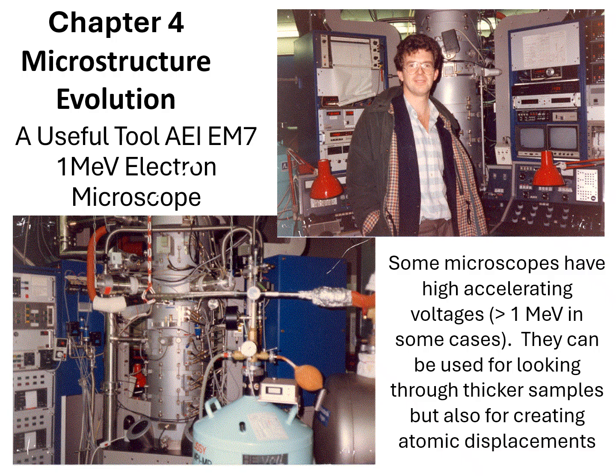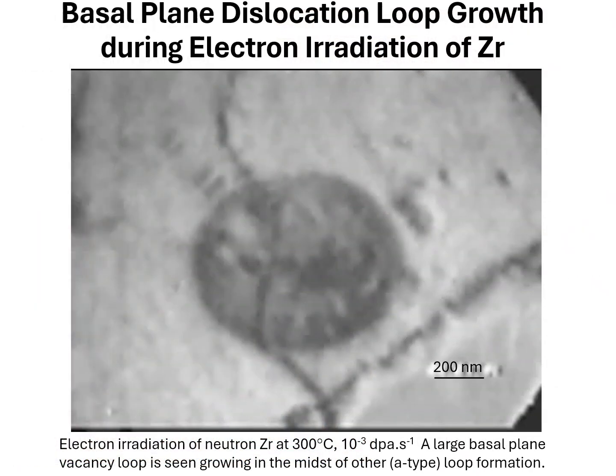Here's an example of one of the experiments I conducted at Stuttgart, and it shows a dislocation loop, something like this, and I'm irradiating it under particular conditions to look at the mobility, to determine the mobility of the point defects.